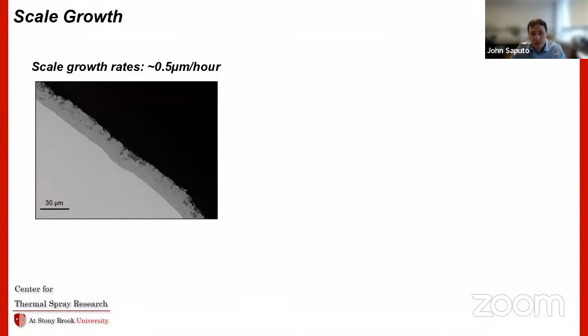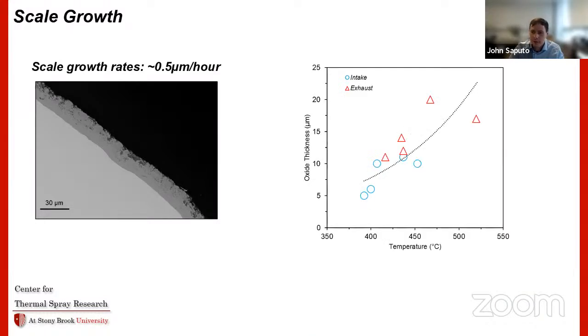If you look at that other region that I called out, is this one, where you have maybe a 20 micron thick scale that forms, which would be a scale growth of about 0.5 microns an hour. And that number might seem small, but you've got to remember that the service lives of these things are on the order of 10,000, 100,000 hours or something like that. So that kind of scale growth for those sorts of service times would be absolutely detrimental to these systems. So you'd be looking at burning through the entire piston by the time that this thing got to see its service life.